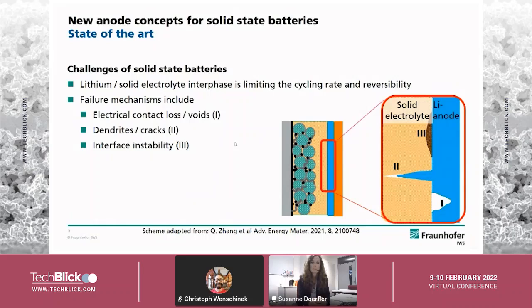We have failure mechanisms that include voids, because we have a rigid solid electrolyte that cannot diffuse into cavities. If voids emerge, we cannot fill them the way we could with a liquid electrolyte. Lithium also has the very unpleasant property of being stripped and plated as dendrites or mossy lithium, and dendrites can grow along the grain boundaries of solid electrolyte particles. It's an intrinsic issue and tough to solve. We also have decomposition: especially when we employ thiophosphates with lithium, a solid electrolyte interface is built.